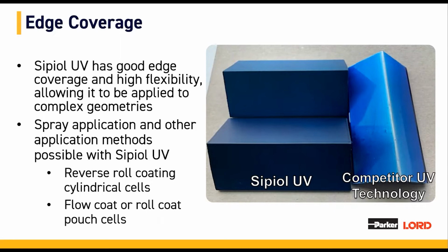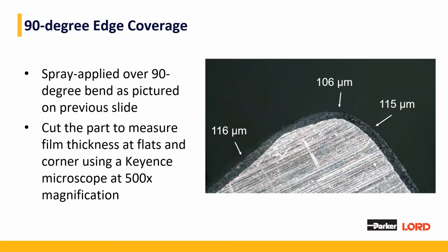The unique property of Sipiol UV's edge coverage allows for easy application on complex shapes and various application styles are possible, most commonly a spray application, but reverse roll coating and flow coating are also possible. This image is a teardown of the 90 degree bend shown on the previous slide. The coating thickness is within 10 microns between the flat edges and corner of the part.